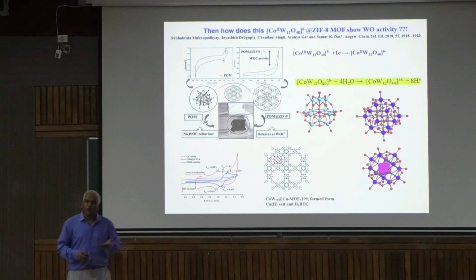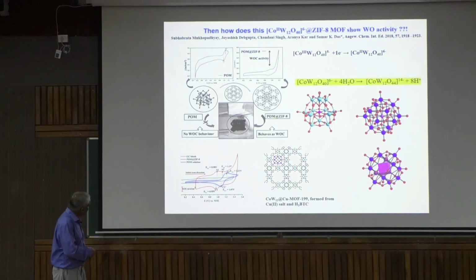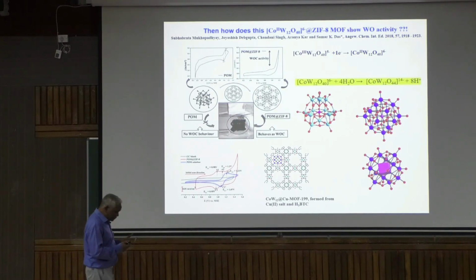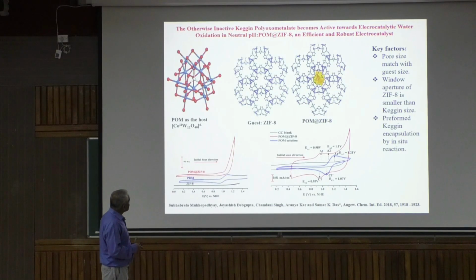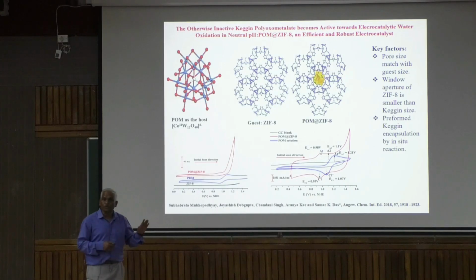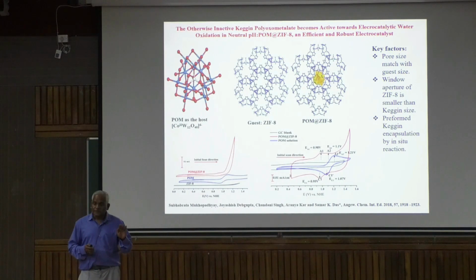Now you may ask me, how do you know this compound will give these 2 couples? Because now it is published by others. They synthesized this compound and did the CV of that compound, and that gives exactly the CV we got here. That means definitely in our earlier paper, what we published before, although we thought it was nothing but that cobalt cluster, the CoW12O40, it is not O40, it is O44. Okay. So that gives the continuous oxygen evolution.